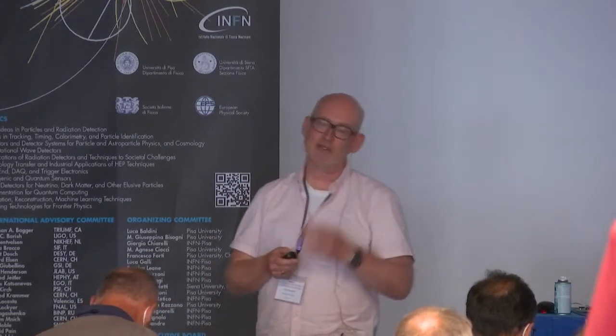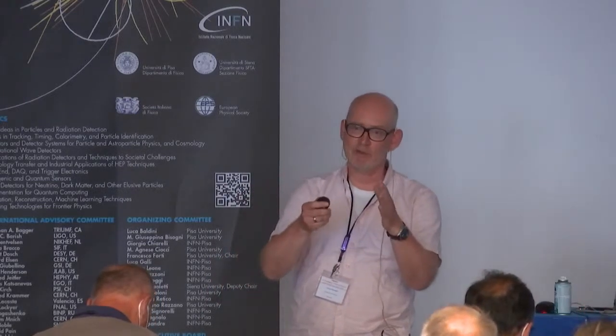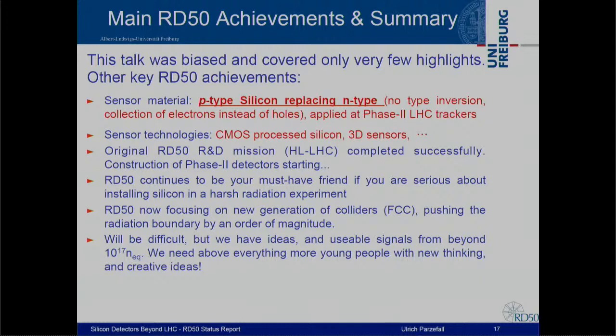Jeff, you are clearly right. Yeah, this is one of the points where a lot of activity is going on in characterizing the defects. But I would be a bit pessimistic here and agree with you that RD50 has not achieved there so much. We have identified defects, but for example, in the carbon case, what we were not able to do is tell from first principles, if you use carbon, this will work better. You will have seen a sketch I had earlier on that seems to show why carbon works, but this is nothing specific about carbon. I think you have a good point there, and I really can't argue against that.